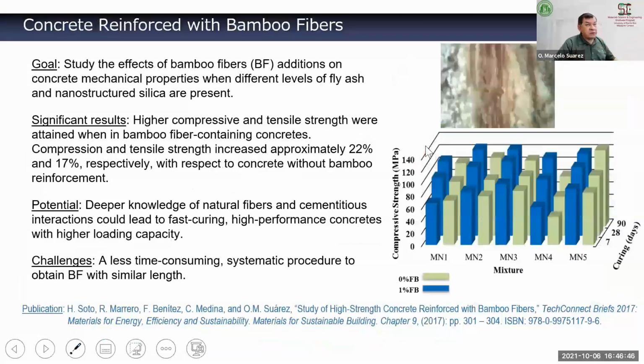One other thing that was a side project, we started adding bamboo fibers into concrete, and we found out that the curing time of that concrete was really fast. So we proposed this to the Department of Defense to produce concrete for airstrips in tropical areas that have been affected by climate change, natural disasters. So you can just put together in very short time an airstrip where you can land heavy equipment, large airplanes, C-130 or whatever airplane you may want to use.